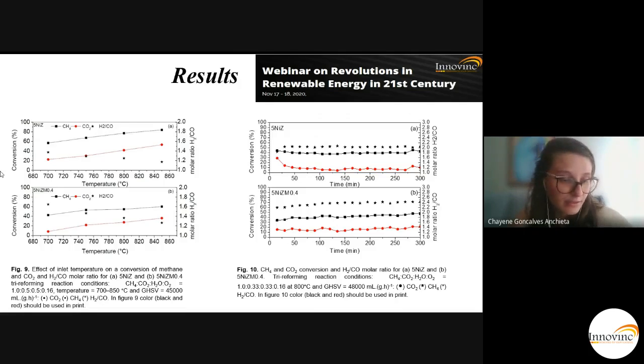And in figure 10, we can see that the nickel catalyst with higher metal support interaction and the lowest particle size has a higher conversion of CO2, and we have the highest molar ratio. This is because of hydrogen and CO. These differences in the molar ratio occur due to the different properties of these materials. We have different crystalline phases, we have different metal interaction. Also, we have different acid-base properties, and for this reason we could improve the CO2 conversion.